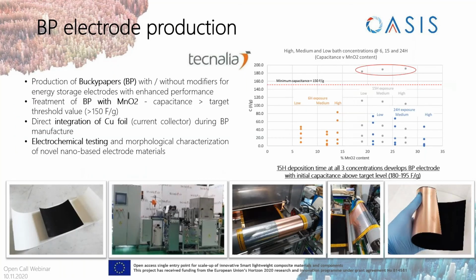Reference Bucky paper electrode performs as well as standard carbon black electrode, but the main goal is to improve the performance of the Bucky papers to outperform materials already on the market. To this end, several manufacturing routes have been explored by Tecnalia to develop customized Bucky papers. Tecnalia worked on different material scenarios, from reference Bucky papers to hybrid formulation Bucky papers with different weight fractions of metal oxides. Moreover, Tecnalia studied different bath concentrations and deposition times, since apart from the metal oxide content, deposition time appears to be critical.